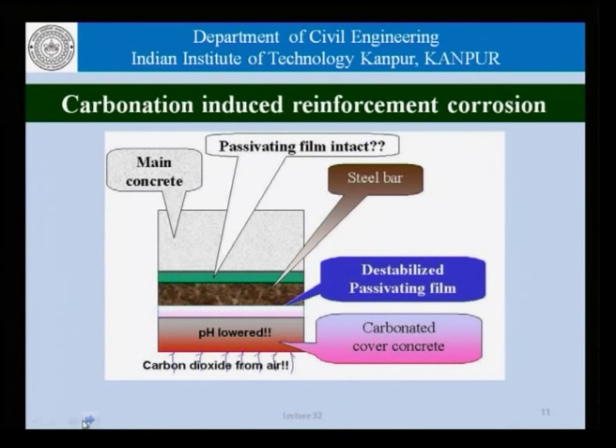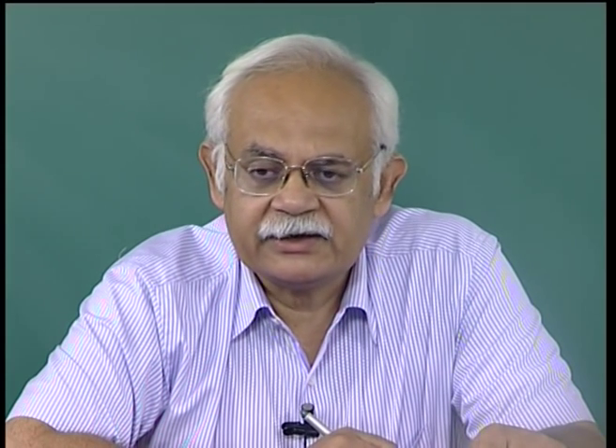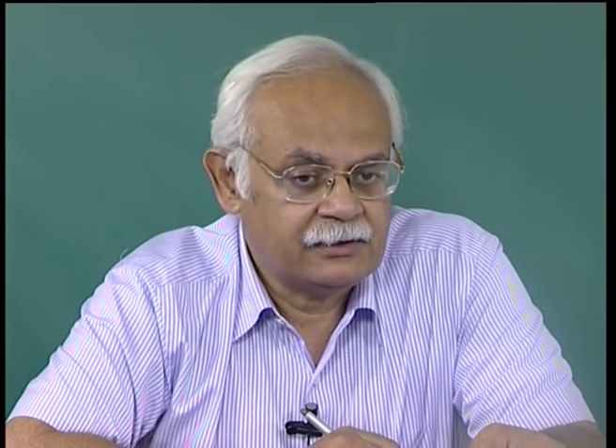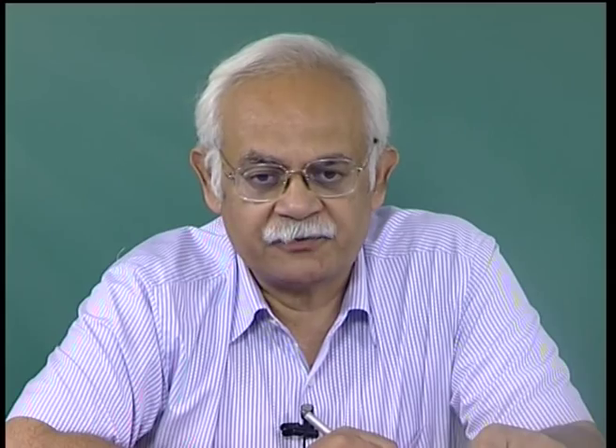So, as far as a carbonated concrete is concerned, what really happens is that once the concrete becomes carbonated as shown here, the pH in the cover concrete is lowered, and therefore, the passivating film in this part is destabilized, and it is as good as not existing, and that renders this surface of the reinforcement susceptible to corrosion. So, as far as addressing the problem of carbonation in reinforced concrete structures from the point of view of durability and reinforcement corrosion, it can be said that carbonation leads to corrosion by the form that,